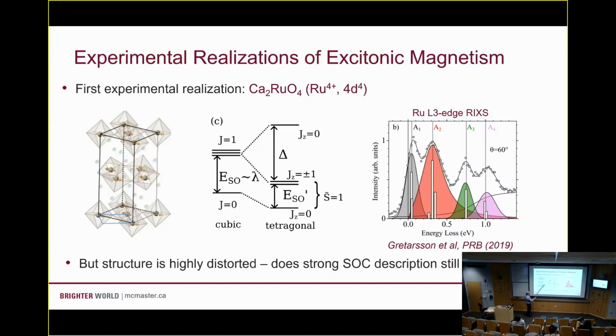Okay? And when we distort the local environment around these rutheniums, we break up the J=1 levels. Okay? And so instead of condensing this triplet, we're actually condensing this Jz equals plus or minus 1 doublet. Okay? So it's still excitonic magnetism, but it's not the sort of Khaliullin picture that we were maybe hoping to find. Okay? So what we're really looking for is a less distorted version of this, which will still give us the same physics.